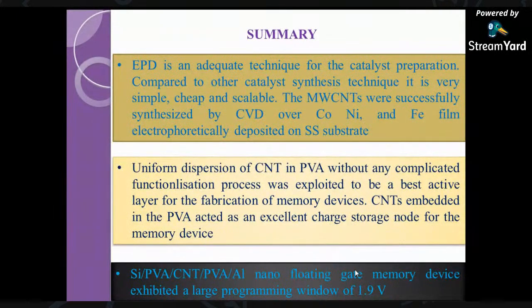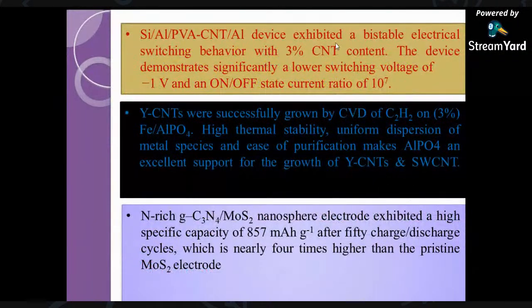When we tried to create the memory device structure, we were able to get good memory characteristics by storing a good amount of charge at around 1.9. And then you have applications of carbon nanotubes in a MIM structure using 3% of carbon nanotubes, where it gives a high ON/OFF state current ratio of 10 to the power 7 at a low voltage of -1 volt.